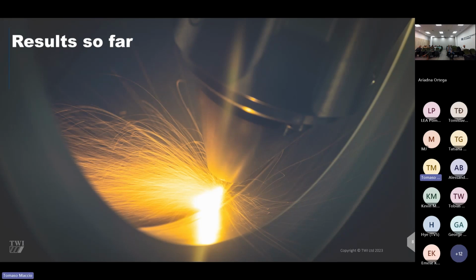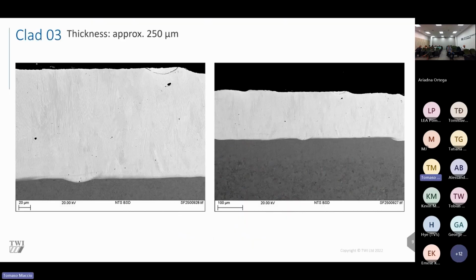I'll go into a little bit of the results so far and the characterization that we completed on selected parameters. Not everything, these are the selected ones that were the most desirable, really the best results that we got. It's important when doing laser cladding, and especially extreme high-speed laser application, to balance the parameters right. If you're getting too hot, something that we noticed when samples were too hot, we got hot cracking. This is solidification cracking. When the deposited material is cooling down, we got cracking. We don't want cracking when we're trying to reduce corrosion with a coating on components. So that's something to consider.